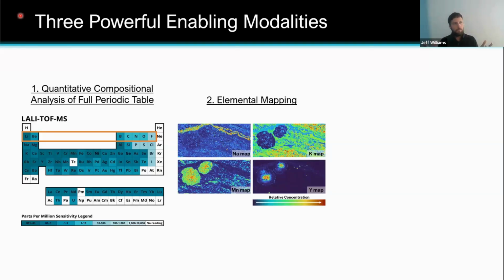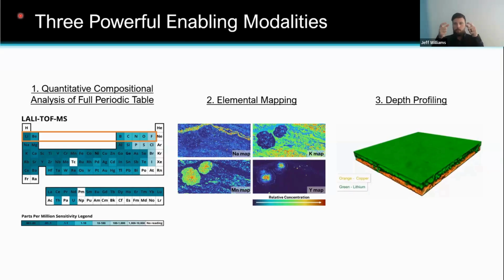So now you might be thinking, well, you're removing a little bit of material. That's about tens to hundreds of nanometers per laser shot, and you're analyzing it. What happens if we just keep repeating it? Well, what we can do is go back over that raster area, that's what we call it, and we can then create a 3D profile and look in three dimensions and map out, what does that look like as we go down? Is it homogeneous? Is my lithium distributed how I expect it to be? Am I getting layers or contaminants that are piling up in certain areas? And so Ellen's going to walk you through an application where we looked at that, where we went all the way through an anode to be able to better understand the chemistry for a customer.